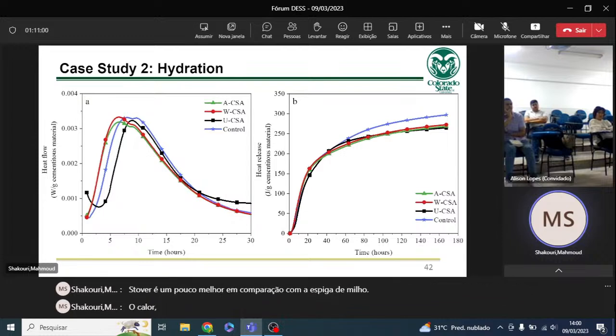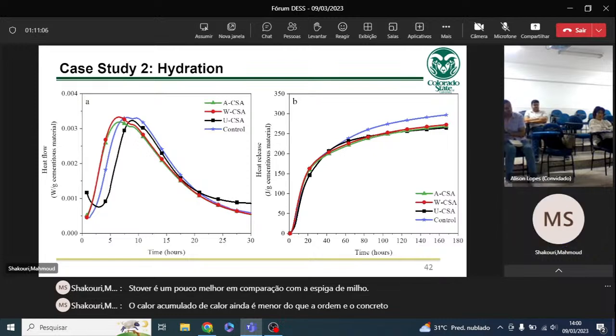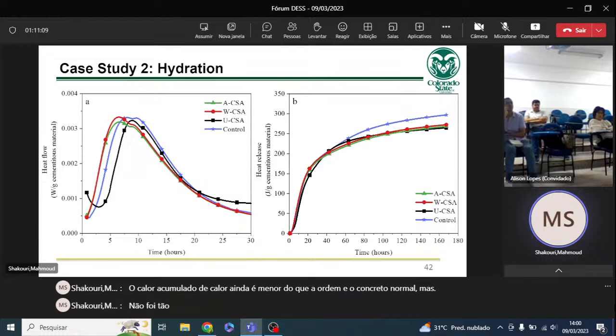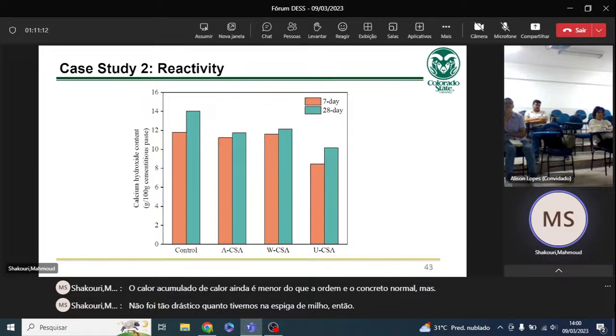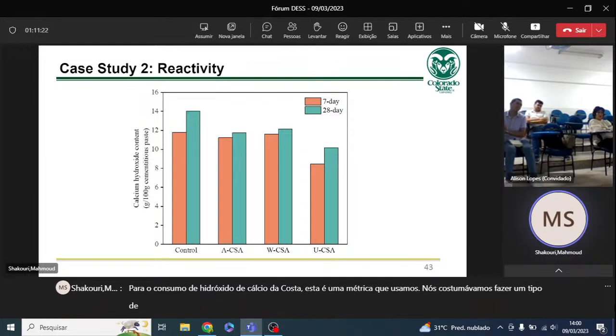The cumulative heat is still lower than the normal concrete, but it was not as drastic as we had in corn cob. So for calcium hydroxide consumption, this is a metric that we use to show how reactive the ash is. The more consumption, the better your ash. So you want your ash to consume more calcium hydroxide. And you can see that both treated ashes had higher consumption than the untreated one.